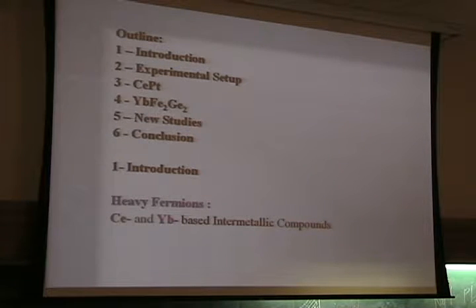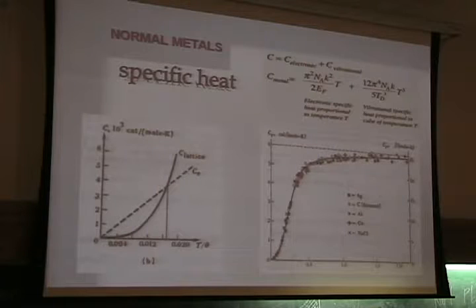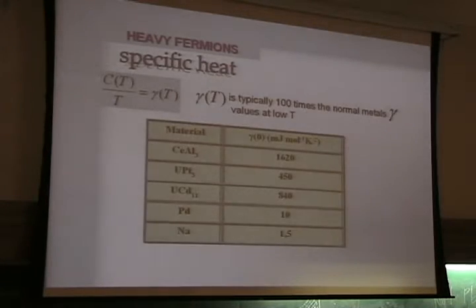So we mainly work with cerium and ytterbium-based intermetallic compounds. For normal metals, the specific heat is dominated by the phonon contribution. Only at very low temperatures, much smaller than the Debye temperature, do you have the electronic specific heat dominating, with this linear contribution given by gamma T, where gamma is this constant here.